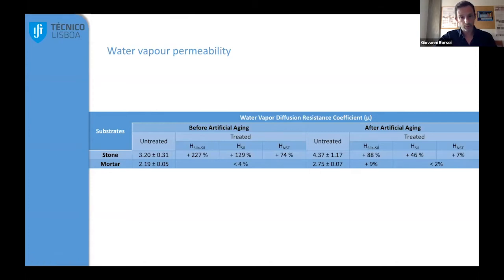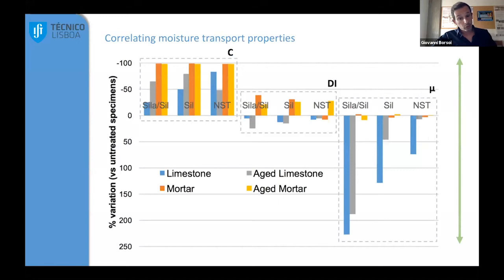water vapor permeability. Once again, the limestone has a very different behavior when compared to the mortar, where the porosity is much higher, the pores are bigger, and so the reduction is lower because the product cannot completely fill the porous network. And so basically we can somehow resume what we have seen in the previous slides.